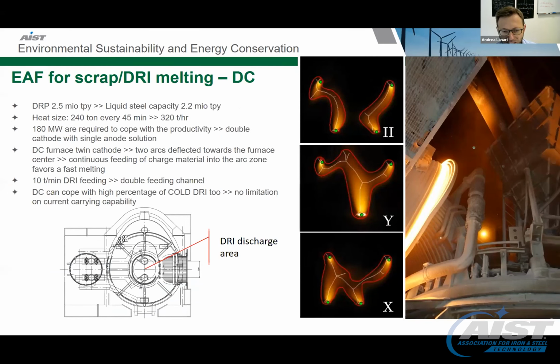First point I would like to touch is the utilization of DC technology on the electric arc furnace for DRI. This is very important specifically when we are talking about big heat size furnaces, 240, 250, 260 ton furnaces that could cope with 2.5 or even bigger modules of DRI. Here we have a need of energy which is very high. As active power we are required to have 180 megawatt, which is a very high power.